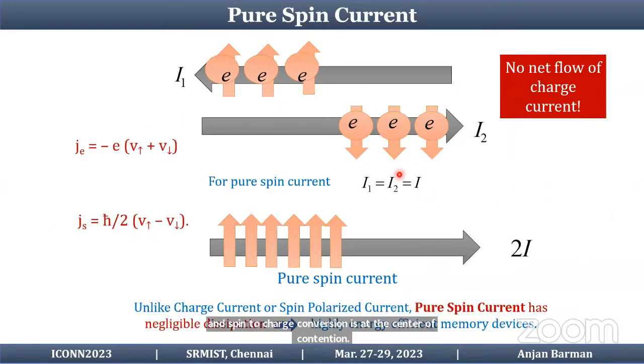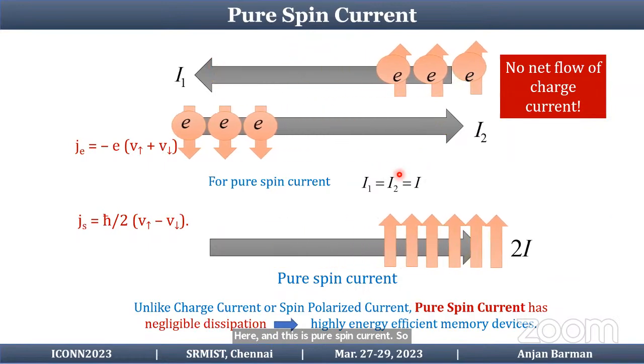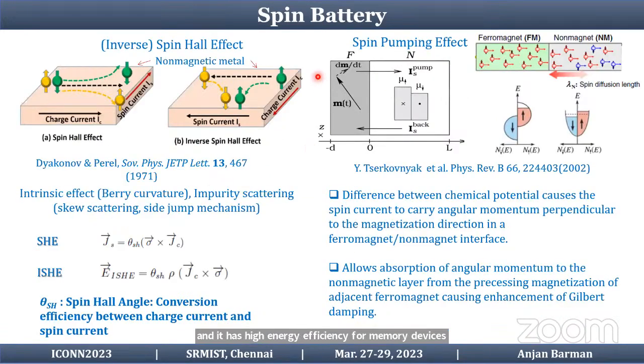And this is pure spin current. If you have spins with two opposite polarities flowing in opposite directions, then there is no net flow of charge current. The charge current is given by this, where v up and v down in opposite directions will cancel each other. Whereas the spin current is given by this expression, where v up minus v down, with spins flowing in opposite directions, will add up and give rise to a net flow of spin current. So pure spin current has negligible dissipation, unlike charge current or spin polarized current, and it has high energy efficiency for memory devices. So for that, we need a spin battery or source of pure spin current, and the spin Hall effect and spin pumping effect are two effects for that.